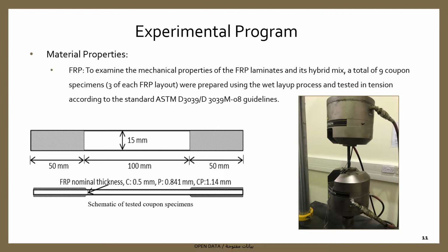In order to examine the mechanical properties of FRP laminates and its hybrid mix, each FRP laminate configuration was repeated 3 times to ensure accurate and consistent results. The compounds were prepared using the wet layup process, cut using a milling machine to a dimension of 200 mm by 15 mm, and then tested in tension.